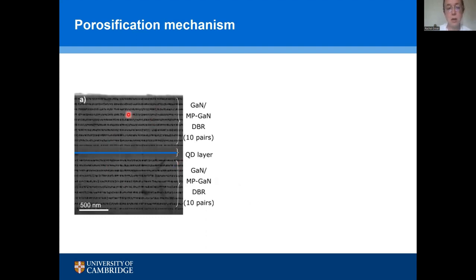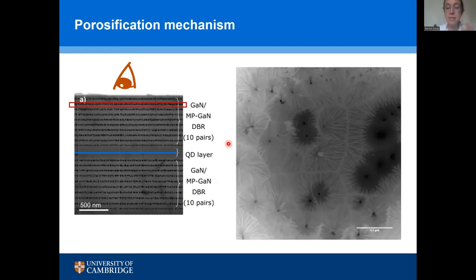So this is just another of these porous structures we've etched here, with two distributed Bragg reflectors, top and bottom, above a quantum dot layer in the middle. What I'm going to do is show you some transmission electron microscopy data where we've made a very, very thin foil that contains just one of these porous layers. We've taken that sheet of material out, and then we're going to look at it in plan view. So this is meant to be an eye looking down on the top of my sample. And what we're looking through is this thin lamella that we've cut out from this gallium nitride stack. And this is what we see, not now from the side as here, but from the top.